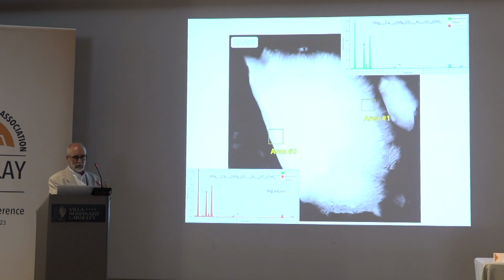We always have, everybody that has worked with the structural formula knows that there is at least one element when we don't know where it is exactly located. Here the problem is magnesium, as always, because we didn't want to change the exchangeable cation with another one. We prefer to use the sample in the natural state. But here in the core, the analysis doesn't close because we have, in this case, an excess of magnesium. So in the core, in this fiber, the core is enriched in magnesium compared with the saponite clay.